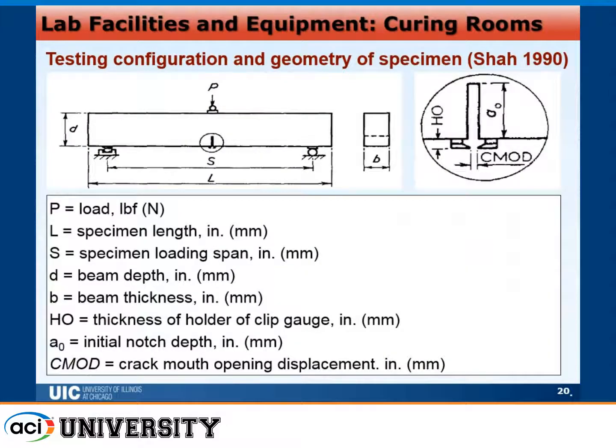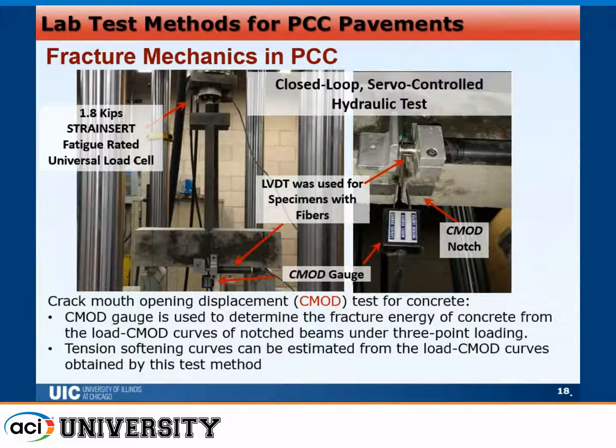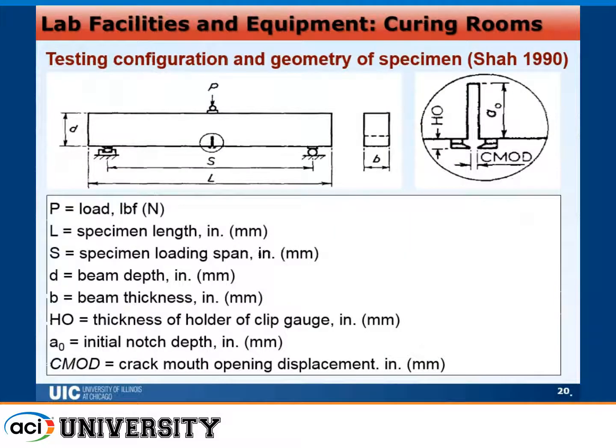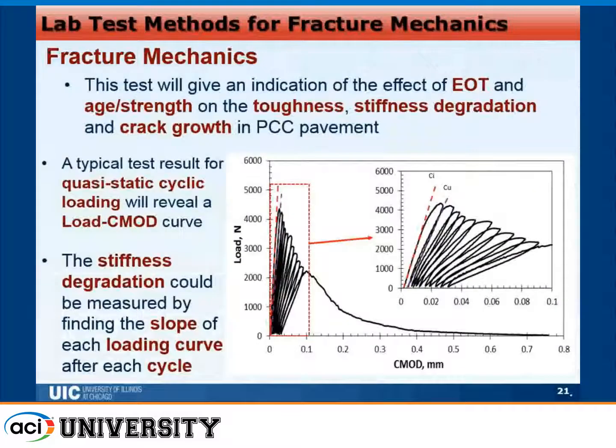And this is the setup that I was talking about. It was taken from Shah 1990. Load P with supported span S, and the thickness of the loading clips was taken into account. These loading clips here were glued using epoxy, and the CMOD clip gauge was attached in the middle so that when you apply the load, it will open at the bottom, and the CMOD gauge will pick up how much opening you have. All these parameters were taken into consideration, and the initial notch length, A0, was also taken into account.